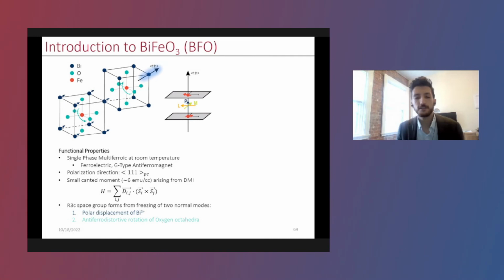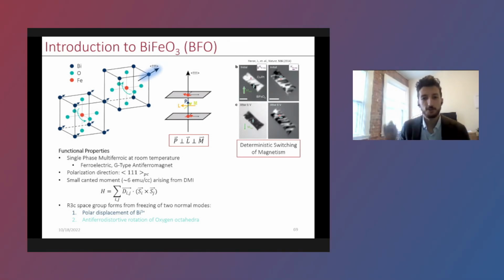But the most important thing that you should remember about bismuth ferrite is that the polarization, ferroelectricity, the Néel vector, and the small canted moment are all orthogonal. So if you get lost, it's just a right-hand rule between all three of them. The other thing to keep in mind is that these three are all coupled. So if I reorient one of them, I also reorient the other two. This has been demonstrated a few times: if I switch the polarization with an electric field, I also switch the Néel vector and the canted moment vector as well. So you can get deterministic switching of magnetism in this material.